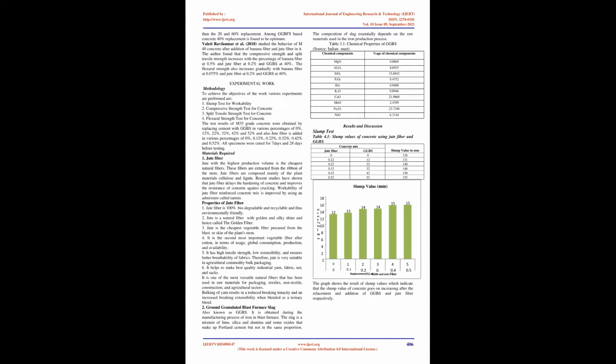Literature review. Vijayalakshmi R., 2021, investigated mechanical properties and crack arresting mechanism of natural jute fiber used as reinforcement for lightweight concrete masonry prism. Study: for the load deformation pattern, jute fiber reinforced masonry prisms were subjected to axial compression load. From the stress strain behavior, it can be concluded that jute fiber reinforcement in foam concrete helps to improve the pre-cracking behavior and prevents the formation of major crack planes in masonry units. From the study, it can be concluded that lightweight foam concrete with fiber reinforcement can be used as a better alternative to clay bricks and aerated concrete blocks.